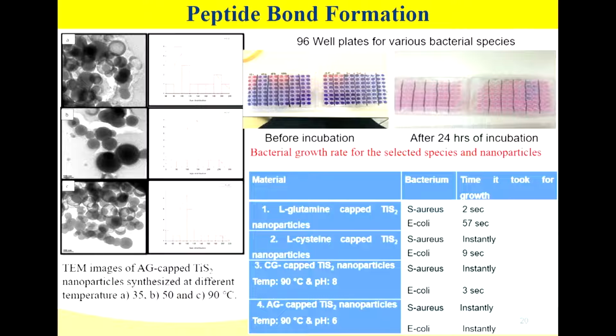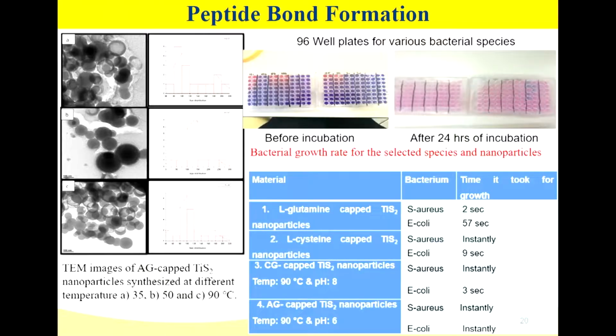At first, we also used titanium disulfide against these particular amino acids. But when you combine them, you find that most of the time there are a lot of interactions such that instead of having the opposite effect, they end up accelerating the multiplication or growth of bacteria. It's not necessarily a bad thing, still a positive thing to explore further, to ask what is really happening here. Is it about the titanium sulfide, or is it the peptide bond that is forming that is encouraging the growth of cell walls in the bacteria? Therefore, it does the opposite of what we intended.